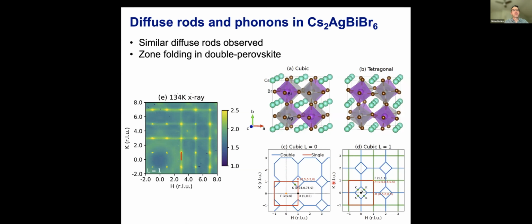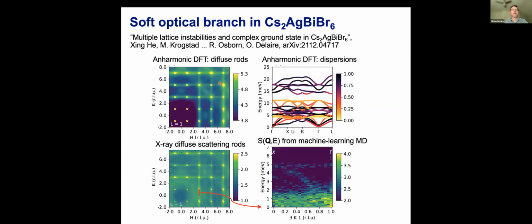The rods are still along the edges of the parent simple cubic perovskite, but they are now going through some zone centers of the double perovskite notations. The correspondence between double and single perovskite is shown in these plots here. It gets a little bit complicated, but I'll try to simplify it for you. So the main point is that now this actually goes through some zone centers in reciprocal space. And so we can do our modeling in these systems also. We can reproduce the diffuse rods, and now because this is happening